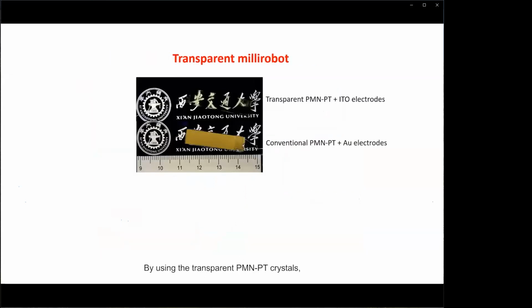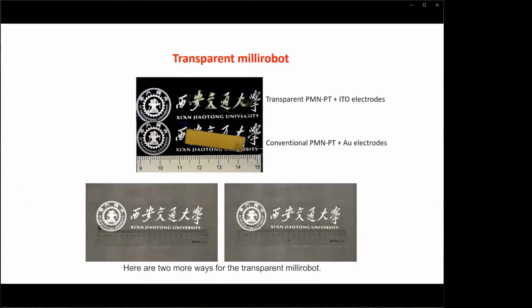By using the transparent PMN-PT crystals, we designed a bimorph structured milli robot as shown here. We use ITO as the electrodes for transparent PMN-PT crystal. This figure shows the comparison between the transparent bimorph device and the device made by conventional PMN-PT crystal with gold electrodes. Here are two movies for the transparent milli robot.